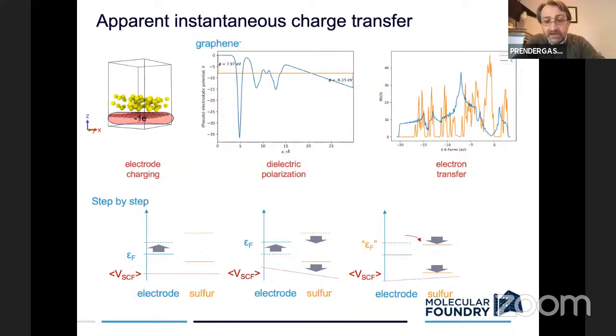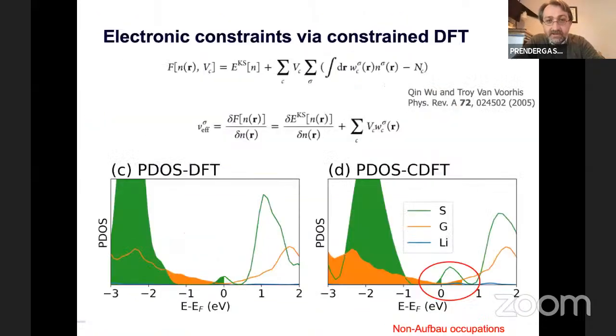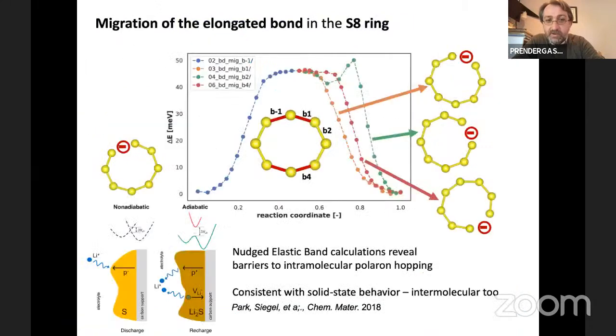Now, if we imagine that the charge transfer is a polaron hopping mechanism, then it's kind of a serial process. So the thicker the surface, the longer time it would take for the charge to come in from the outside, if it's a lithium ion working its way through gaps, or for the electron to emerge out towards the lithium ion to meet it. And so it should be a slower process, and it's just a series of potential barriers that have to be overcome, much like ions moving in intercalation in solids.